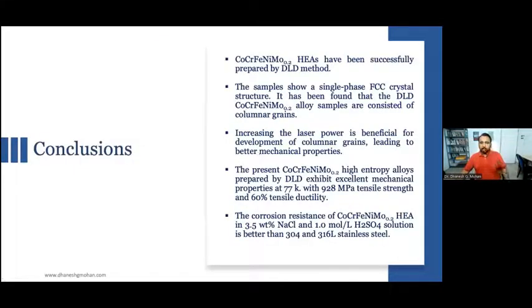From these results, we concluded that we can fabricate a high entropy alloy using additive manufacturing. The structure we found is a face-centered cubic structure. While increasing the laser power, more and more columnar grains are found. Up to 1200 watt, it enhances the mechanical property. After that, the mechanical property drops because the size of the dendrites is increasing and the amount of fine grains is decreasing. Due to this decrease of the fine grains, the mechanical property is reduced.